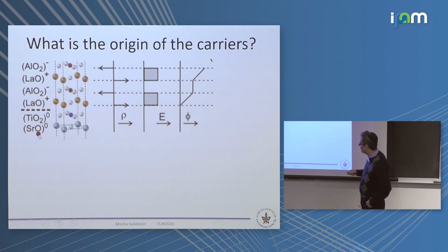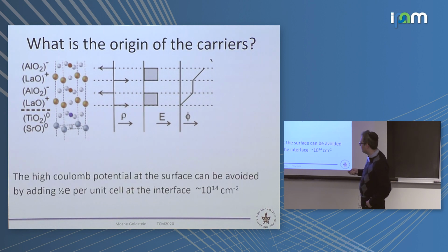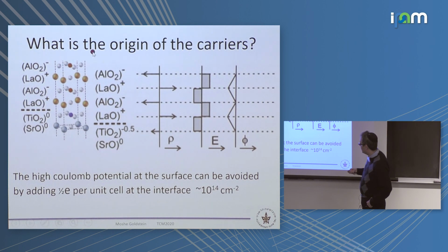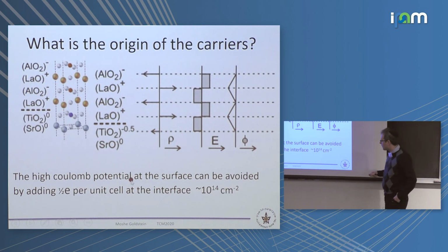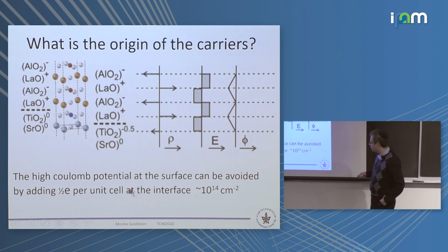And the first thing to break is strontium titanate. So if you have enough layers, and the number is indeed roughly 4, then you are going to create a very big potential difference, bigger than the band gap of the strontium titanate. Then what the system is going to do is move electrons from the top layer into the interface, into the titanium orbitals, because this is the conduction band. And if you put here a layer with charge of minus half density as compared to the other layers, then the electric field will oscillate up and down, and the potential will not accumulate, so the system will be happy.